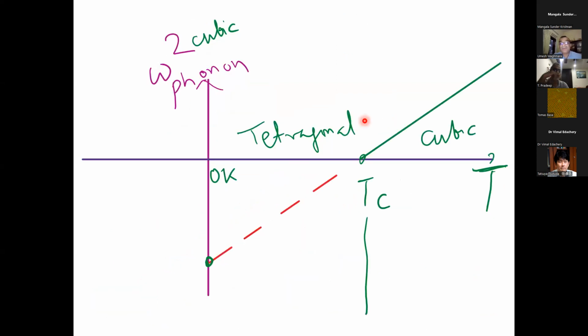Now, if you think about a phase transition in this framework, what I'm showing you is the frequency squared of a phonon of the cubic phase, which is unstable at low temperature. You see at high temperature, the phonon frequency drops very close to zero. This is called a soft phonon near the transition temperature. In fact, the concept of soft phonon originates from Bangalore as well. C.V. Raman in 1939 talked about this in the quartz phase transition, the alpha to beta phase transition in quartz.